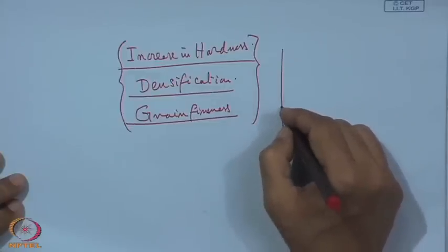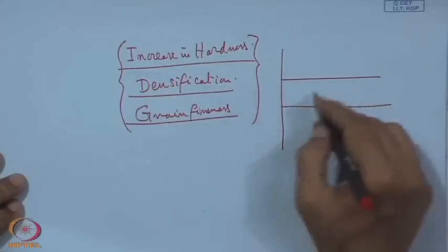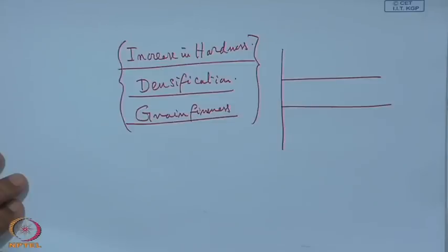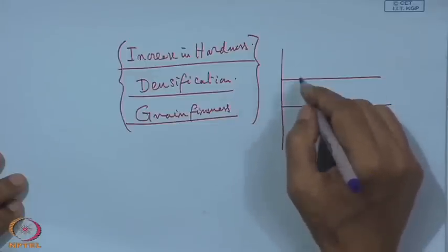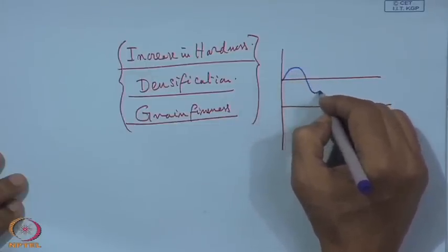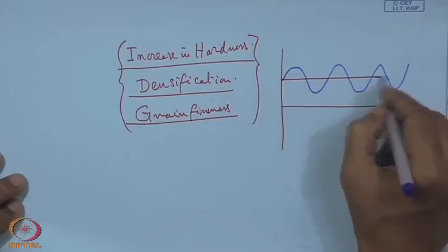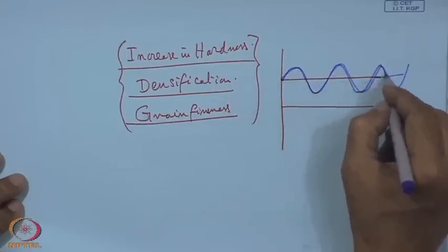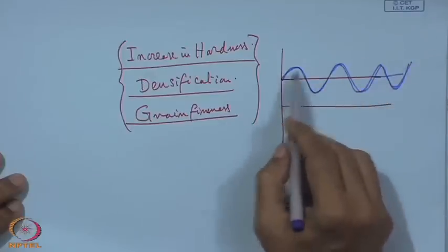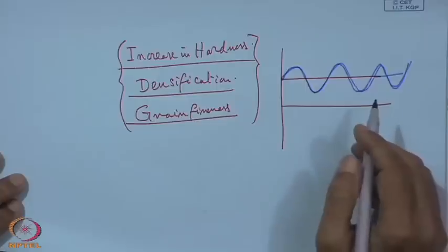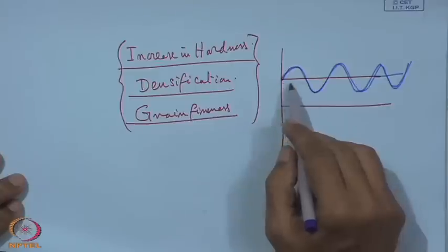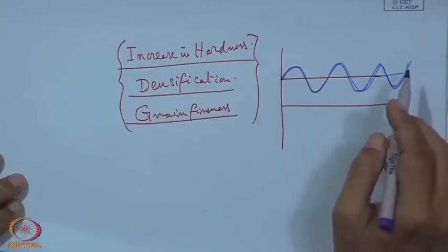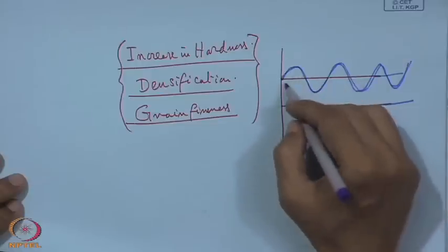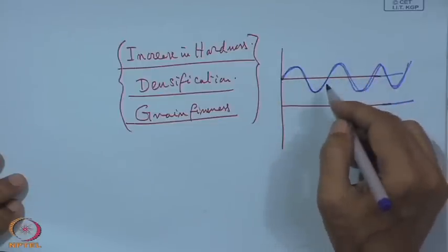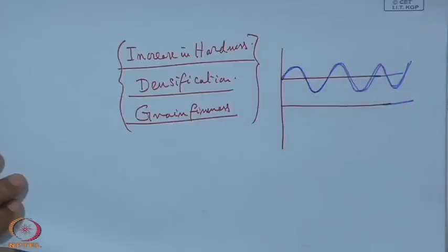And in certain cases there has also been some attempt that normally if we consider this is a DC from the cathode side, over that also one AC can be superimposed. So, this is a DC, over that it can be like this. So, finally, what we get is that this voltage is continuously changing, and by that change some good results are expected. So, a DC bias with a sinusoidal AC which is superimposed over this polarized bias DC, that is also being used for this pulse deposition mode.